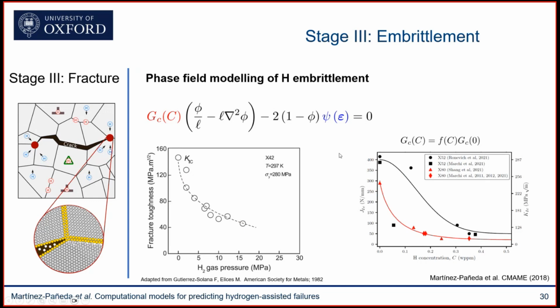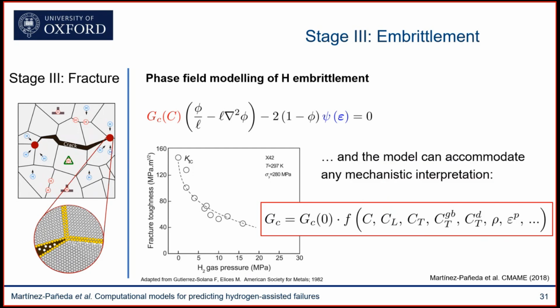And this is often good enough because many of the materials that we're interested in, we have characterized them properly, and we understand them very well, and we have data of fracture toughness versus hydrogen content. So there's no need for us to go beyond that. But we can go beyond it. For example, if we're thinking of designing metals with resistance to hydrogen embrittlement, we need to go beyond that. We need to be fully mechanistic. And the good news is that this framework can accommodate any mechanistic interpretation. So you can define your hydrogen degradation function as a function of any micromechanical or macromechanical parameter that you believe is of interest: the hydrogen trapping in grain boundaries, the dislocations, the plastic strain, dislocation density, whatever you believe matters. So let me tell you a little bit of what I think matters.